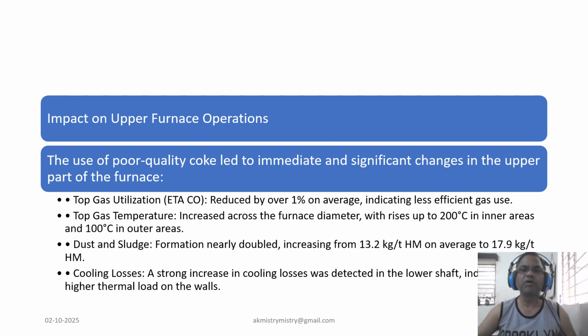The furnace's reaction was swift, especially in the upper section. The top gas utilization, a key measure of efficiency, dropped by over 1% on average, meaning the gas was doing less work. Top gas temperature rose significantly across the entire furnace radius, up to 200 degrees Celsius in some areas. This indicates a less stable and less efficient process. Furthermore, the generation of dust and sludge, which must be managed, nearly doubled from about 13 to almost 18 kg per ton hot metal. We also saw a sharp increase in cooling losses in the lower shaft, pointing to higher thermal load on the furnace wall, which is a major concern for equipment integrity.